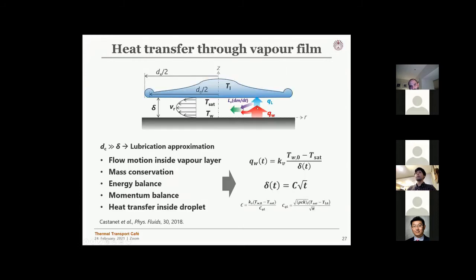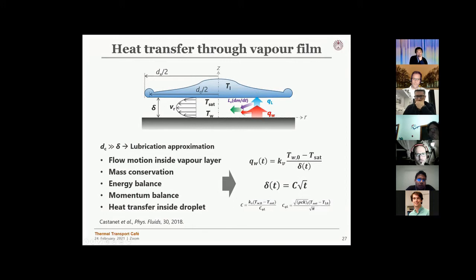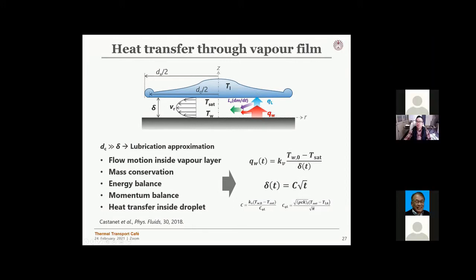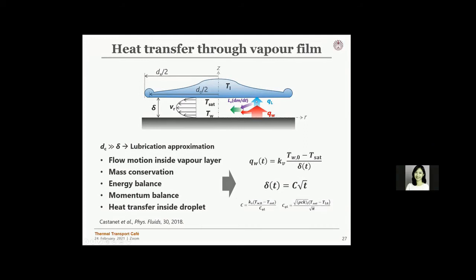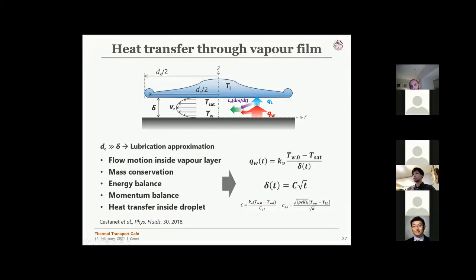As for heat transfer through the vapor film, we follow the analysis by the French group, published in 2018. We have this schematic model: the droplet is floating on the vapor film, and heat from the wall - some of it is transferred to the droplet, some transferred to the vapor. The heat transferred to the droplet, denoted as QL, is partially used for evaporation. So the heat goes like this.